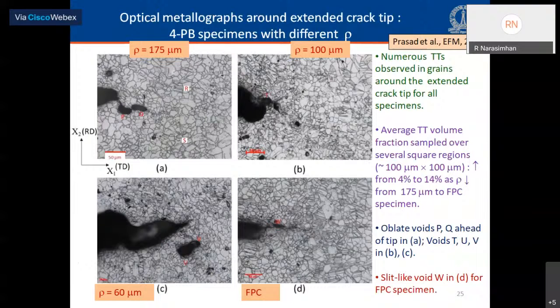Now, these are optical metallographs corresponding to different notch root radii taken from the 4-point bend specimens. And in all the images, we can see twins are present in the grains surrounding the crack tip. We actually quantified this by considering several 100-micron size domains. Prasad did a very systematic job again and calculated the average twin area fraction by doing very painstaking metallographic work, and found that the average twin area fraction increases from about 4 to 14% as the notch root radius decreases from 175 microns to the fatigue pre-crack specimen, which is shown on the bottom right side. That is the FPC or the fatigue pre-crack specimen.